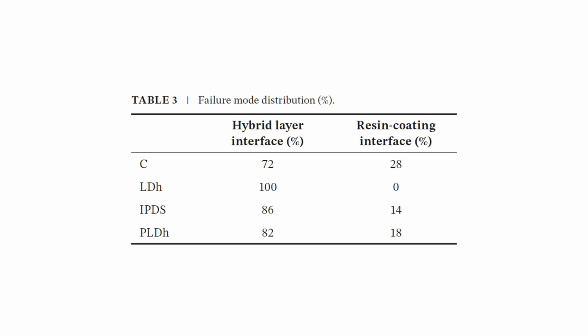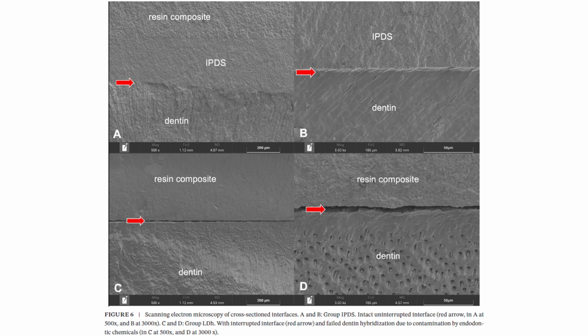And this table shows the failure mode distribution, and overall the fracture pattern results were mostly restricted to the hybrid layer. They also did SEM for some of the samples, and pictures A and B show the dentin sealing group after ultrasonic preparation. It shows an intact and uninterrupted interface. As for pictures C and D, they show the late dentin sealing group with an interrupted interface and failed dentin hybridization due to contamination by endodontic chemicals.